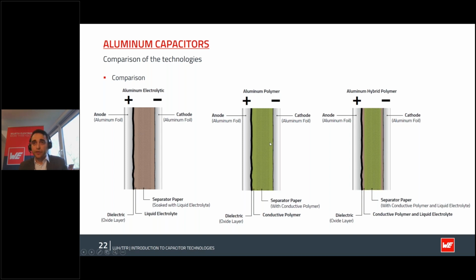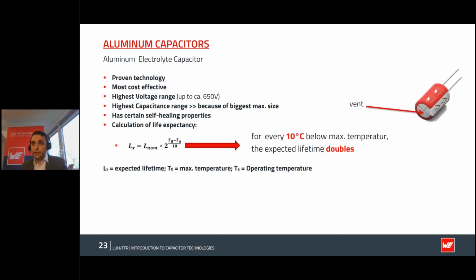On the other hand, you have the aluminum polymer types where we soak this paper in a liquid polymer and then bake it to become a solid polymer. During this process, the polymer will expand, and as we have it rolled up, it will create some tension. So this is why we have a limit in the size we can produce here. And the third way, the newest technology, is the aluminum hybrid polymer types, which have both parts here. They're first dipped into the polymer, then baked, and then also the liquid electrolyte is put in there under some pressure. Now we'll get into the three technologies one by one.